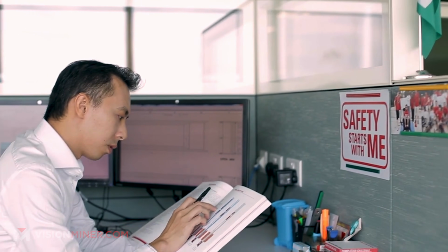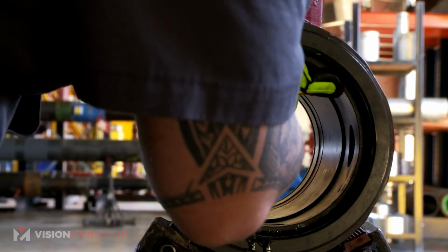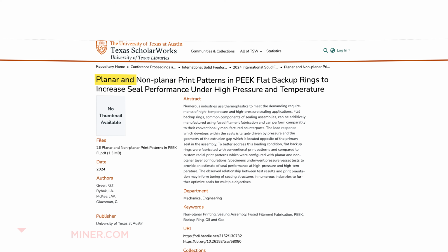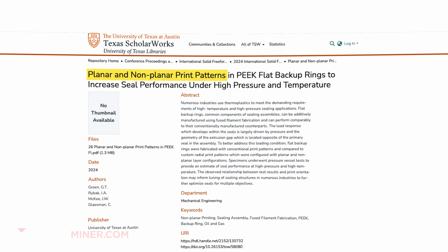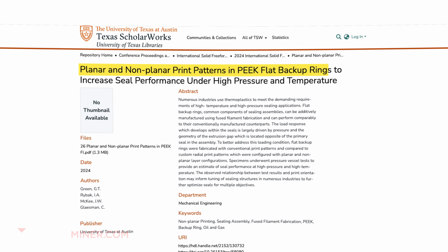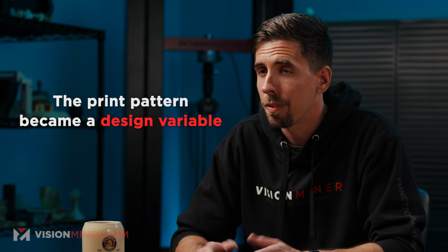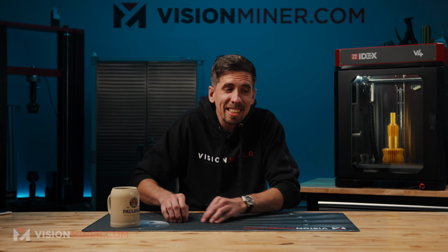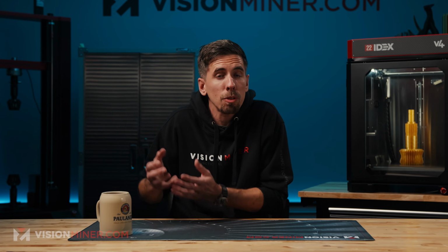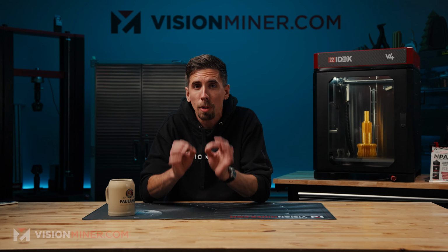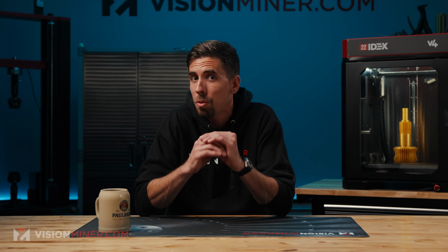A companion paper from the same team went to the Solid Freeform Fabrication Symposium, looking at planar versus non-planar print patterns inside a flat PEEK backup ring. The result? The print pattern itself became a design variable. How the tool paths run inside the ring changes how the ring seals under pressure. And that is the part that most people miss. With a printed part, the tool path itself is a tunable property of the seal, and that's something you cannot get by machining something out of a billet.